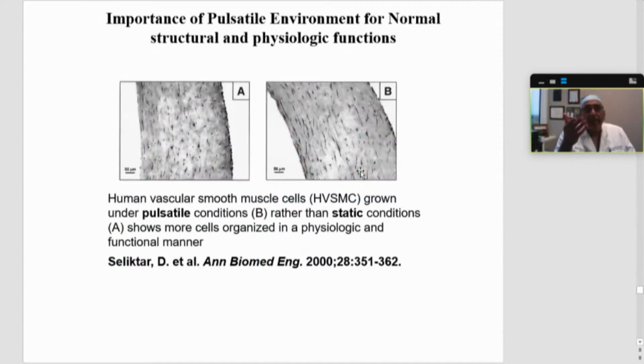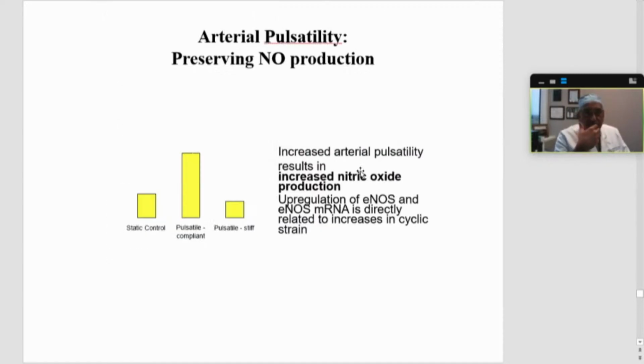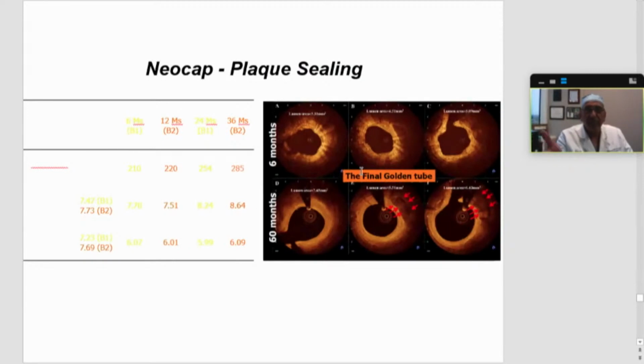For vascular healing. But also, when you put in a rigid metallic stent, you potentially can lose the pulsatility of that particular vascular segment. And human vascular smooth muscle cells grown in pulsatile conditions rather than static conditions show more cells organized in a physiologic and functional manner. So why is that important? Because once you have arterial pulsatility and you have more organized vessel cells, you actually have increased nitric oxide production, with upregulation of eNOS as well as eNOS mRNA directly related to increase in cyclic strain. So that potentially may lead to improved vasomotion as well as better flow.